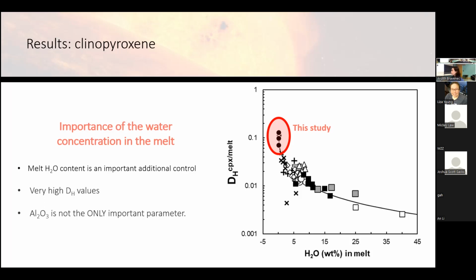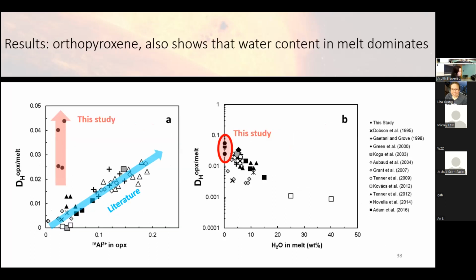So what we see here is that it isn't just aluminum and the incorporation mechanism of the crystal, but it's the surrounding water activity of the entire melt that establishes the partitioning trend. And once we take that into account, we can explain the data once again. And this is just for clinopyroxene, but in fact, orthopyroxene follows the same trend. For nominally anhydrous experiments, you get really high partition coefficients that can only be explained by the water content of the melt.